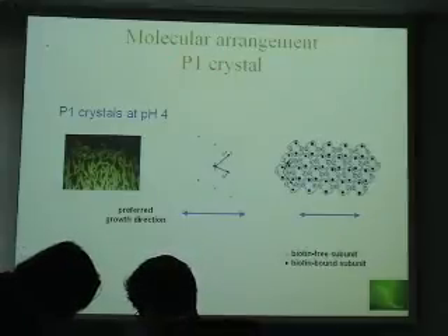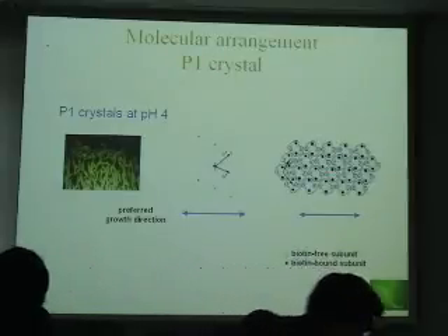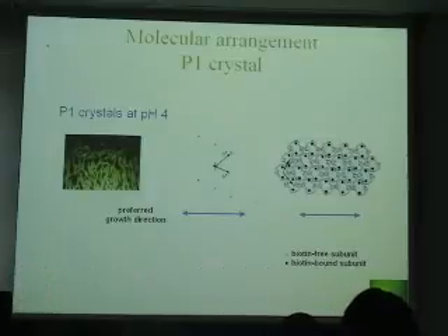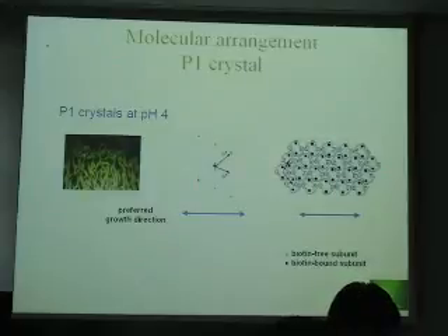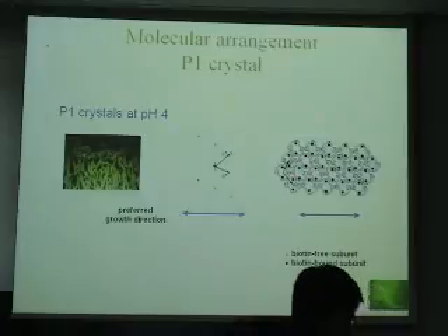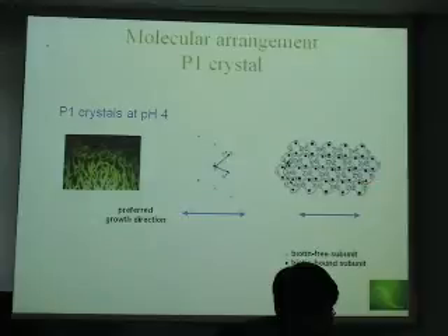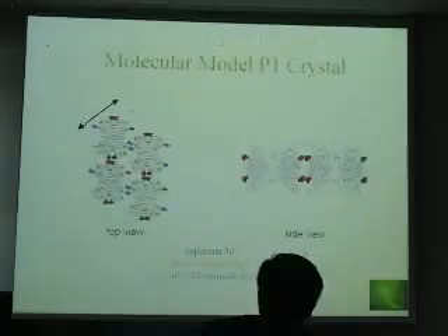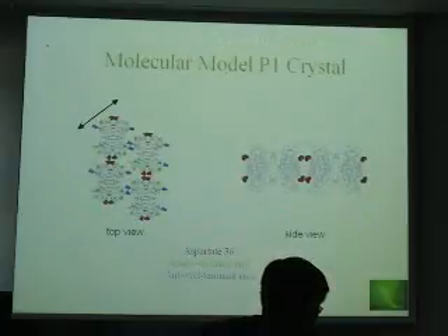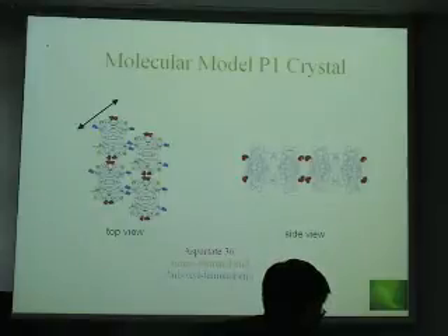We focused our attention on the P1 crystal because it's the most densely packed and gave us the most interactions. And if you look at a model of how they're packed, this being the needle-like direction, again you see biotin bound and biotin free. In this case, the fastest growth direction is kind of along the biotin free subunit direction. We looked in more detail again and tried to identify which amino acids were changing their behavior around pH, between pH 7 and pH 4.